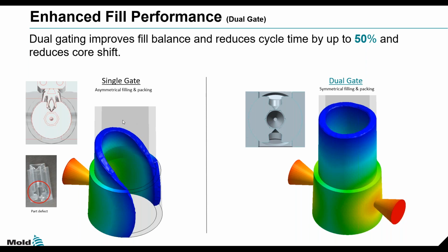That's a problem if this core pin is not located at the open end. If you have an open end in the part, parts like blood vials, you can't shut off on the top of the core pin. So if your plastic is moving up on one side, you may cause that core pin to deflect and get pushed over. If you were doing it with a cold runner, you'd make the cold runner come into the cavity on both sides.